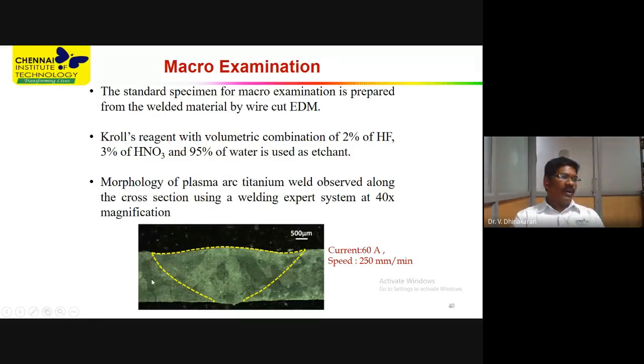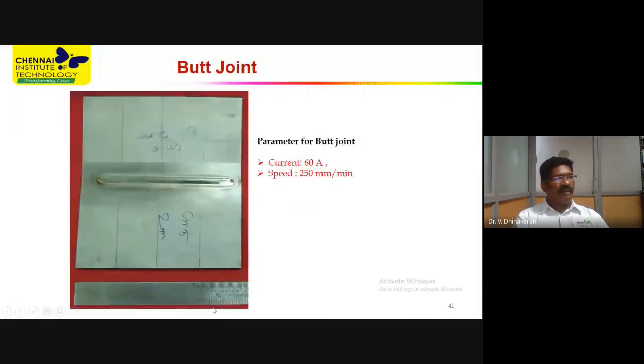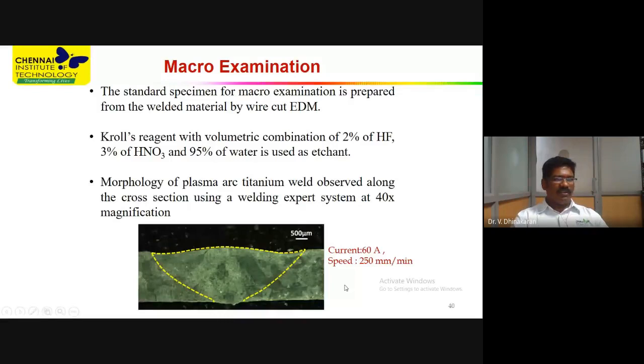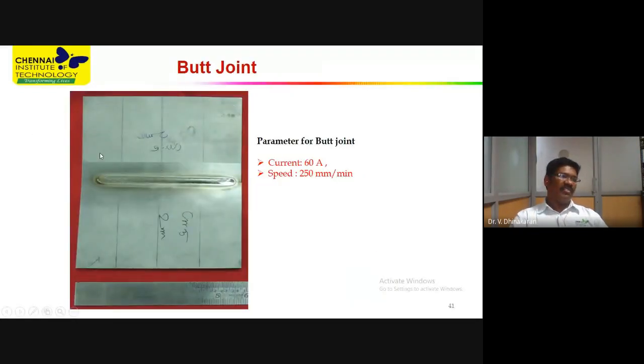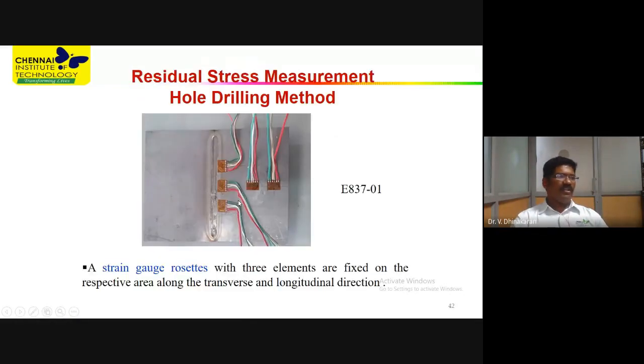Okay. So after welding, we cut the specimens and looked at the penetration of the welding. Then we found that 60 amps current and 250 mm per minute welding speed yielded a full depth of penetration. Hence, that parameter has been chosen for creating the butt weld joint. Then we measured the stress by using the hole drilling method.